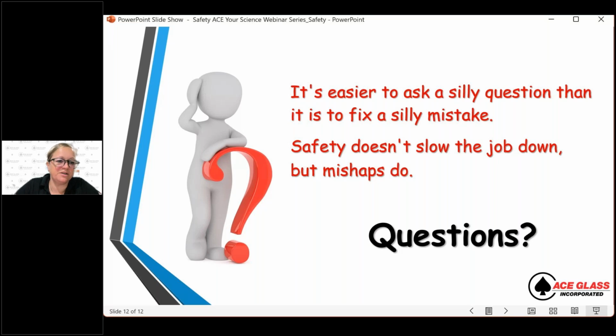All right, let me get over here in my question window. All right, what is the vacuum rating for Pyrex or borosilicate glass? So there are always big debates, right? And people say, well, I have pulled it down to low vac and so on. The rule of thumb is if you have standard bore silica glass, you can go to plus or minus 1 bar. So you should keep it at 1 bar on the positive pressure side and at minus 1 bar on the negative pressure side. Of course, you can always go a little bit lower and inch your way to the real edge there, but that would be the safe range you want to be in.